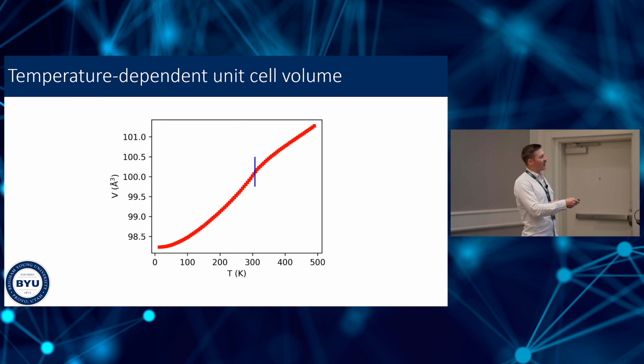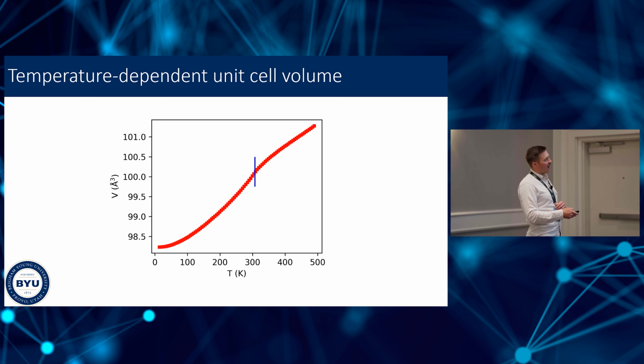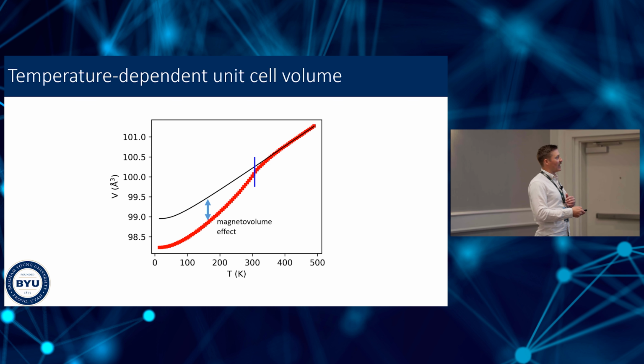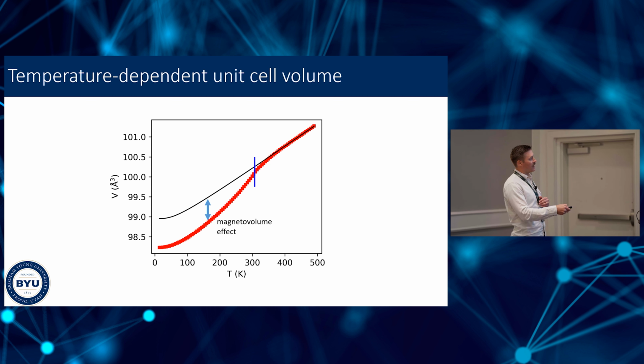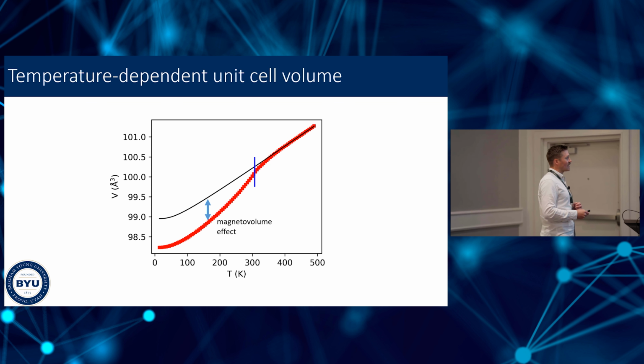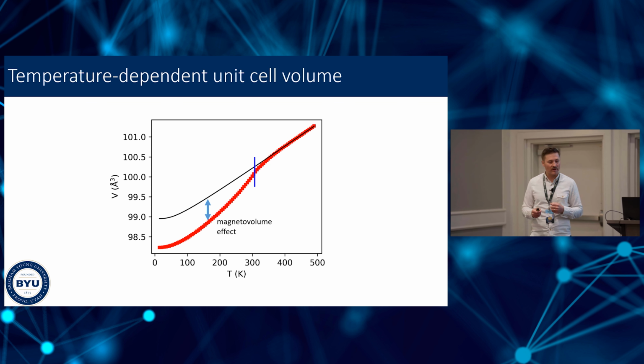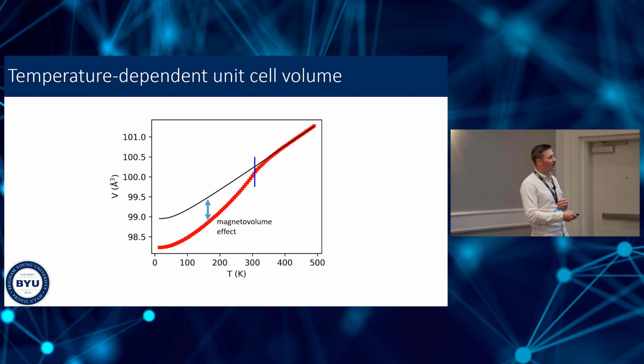And if we look at the volume, here's the unit cell volume right here, we can actually calculate what we would expect the volume to be as a function of temperature using a Debye-Grüneisen model. And that's shown by the black curve right here. So this is what we would expect based on the high temperature linear trend, in the absence of magnetism. The difference that you see here is evidence of the magnetovolume effect. Okay, we're changing the unit cell volume because of the magnetism.